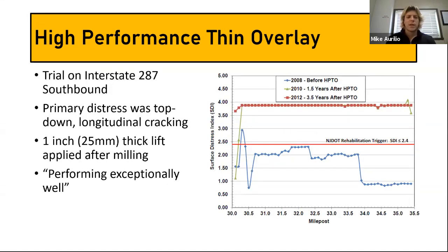So they paved this, they put this overlay on Interstate 287. This specific job's primary issue was top-down cracking. It was a 1 inch, 25 millimeter thick lift, and according to the report, it's performing very well. You can see on the right-hand side how their surface distress index changed after paving, and even 3.5, 4 years after the job, the pavement was still performing very well. And this has obviously then been used to develop some of their cracking criteria moving forward for this type of lift.